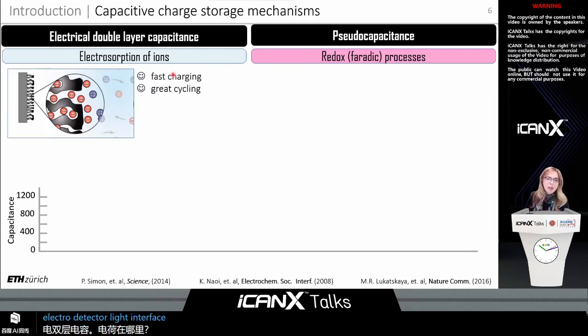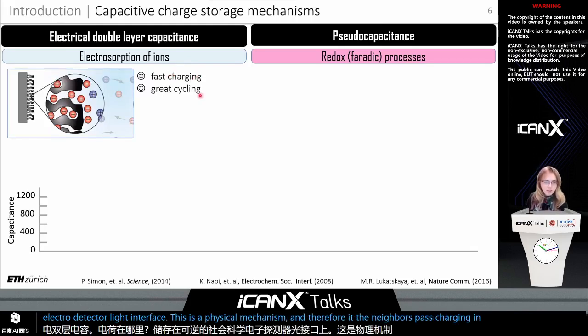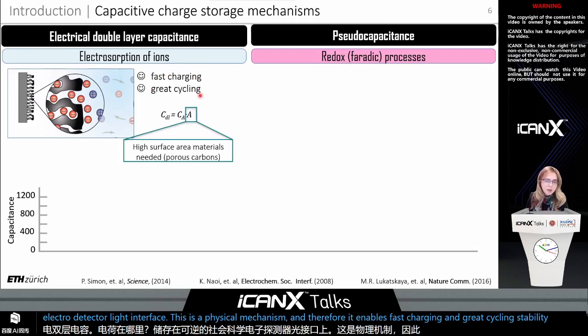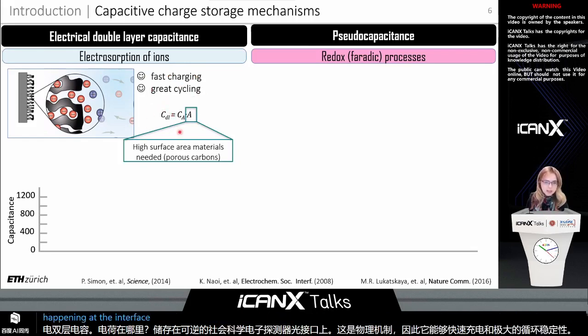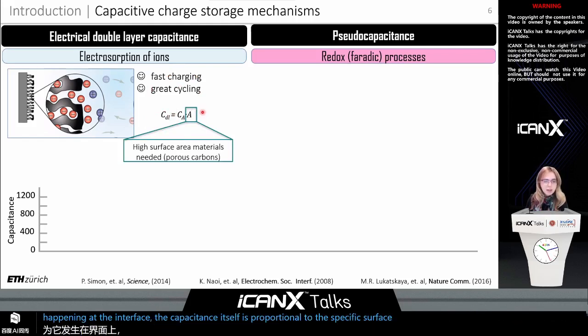This is a physical mechanism, and therefore it enables fast charging and great cycling stability. Since it's happening at the interface, the capacitance itself is proportional to the specific surface area of the material, and that's why the materials that really champion this charge storage mechanism are high specific surface area porous carbons.